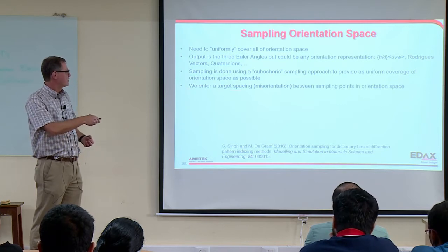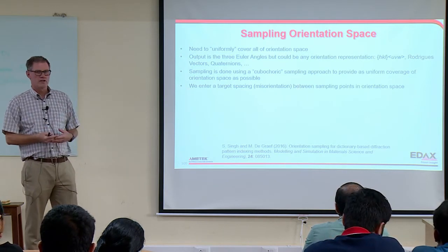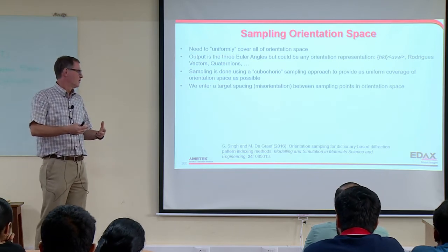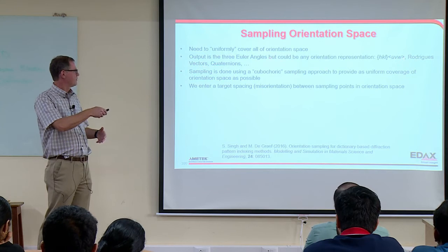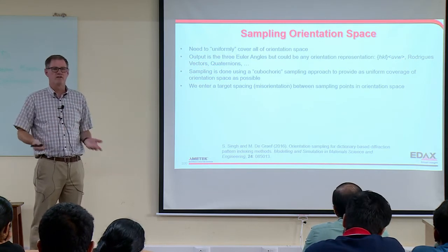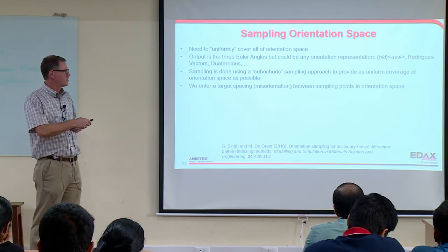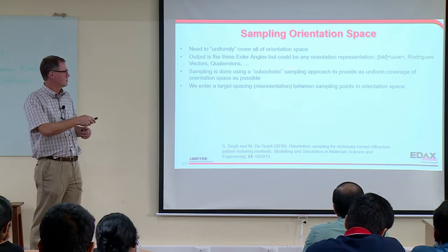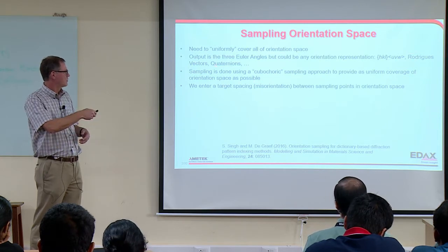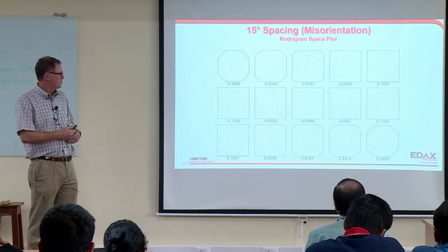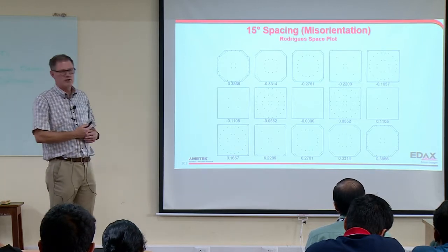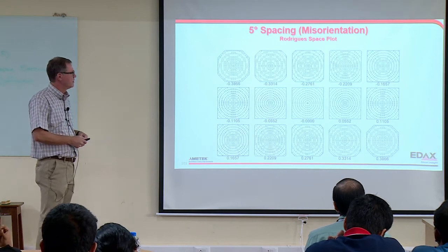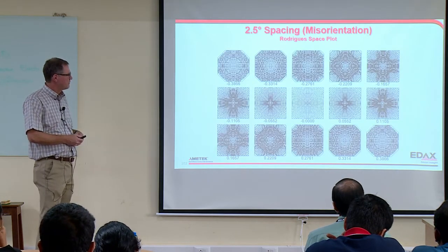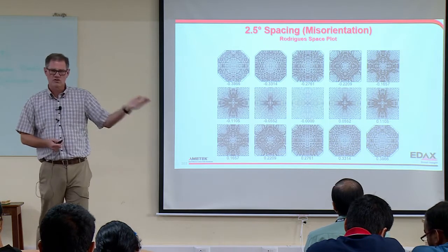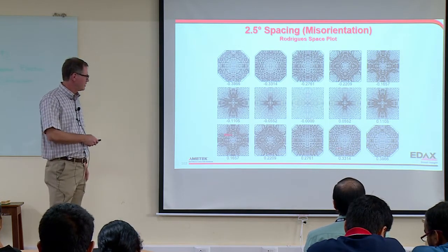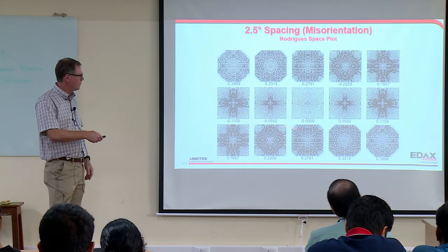But the idea here is we enter a target spacing between sampling points in orientation space. So if we were in Euler space, we have 3 Euler angles, we would have 5 by 5 by 5 degree orientations. But Euler space is nonlinear, so this idea doesn't work. That's why we use this sampling. We could do it in any space, Rodrigues vectors, quaternions. And this just shows it in terms of Rodrigues vectors. Here's a 15 degree spacing in orientation space, 5 degrees, 2.5 degrees, and after I go smaller than that, it pretty much just goes black and I can't show it to you. So you can see in orientation space it's somewhat uniform. You can really see it here.